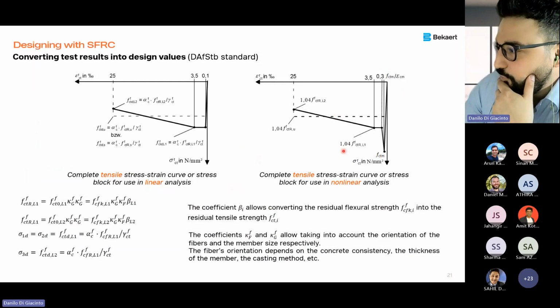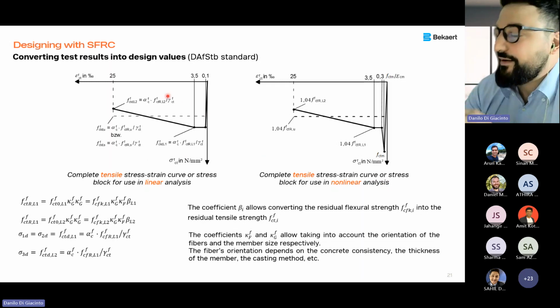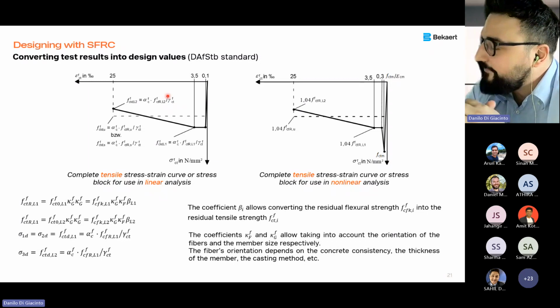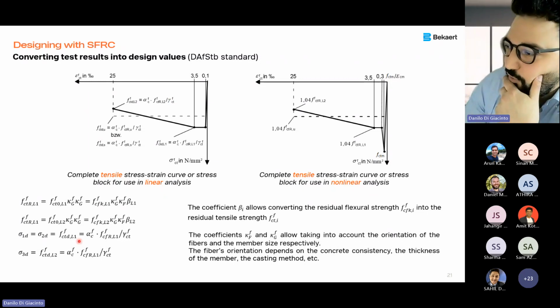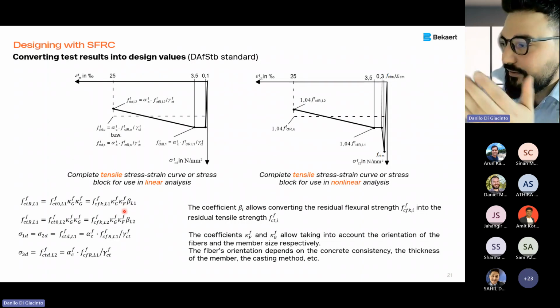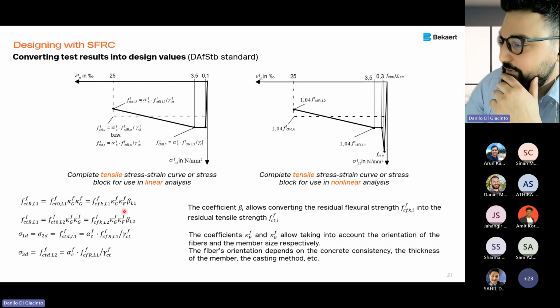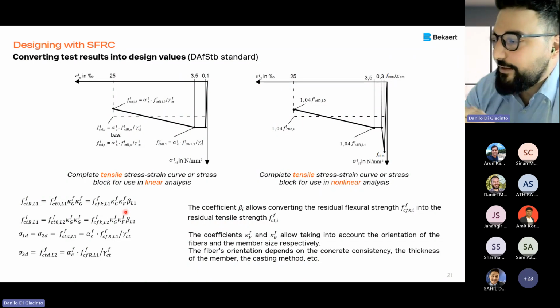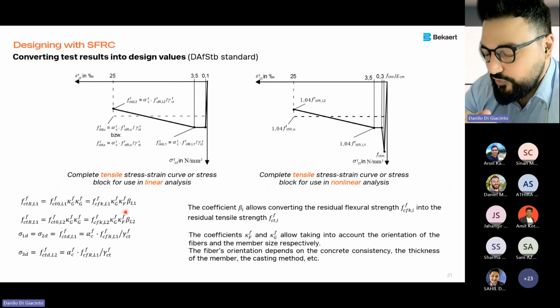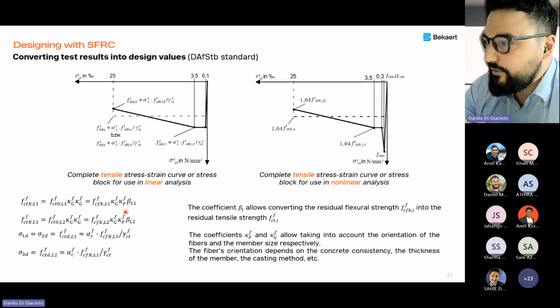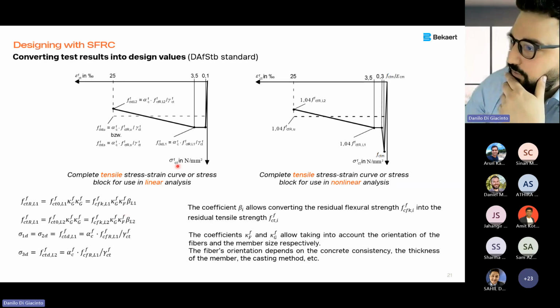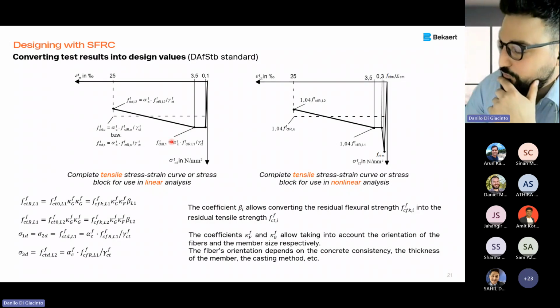This is a nice slide with two tensile loads. This one is used typically for linear analysis. This one is used typically for nonlinear analysis. Those tensile loads come from the German standard, which I told you is very comprehensive and covers every aspect of SFRC. You can see here the coefficients I was talking about previously, and those coefficients depend on the properties of your concrete and the element you are investigating. There are very simple formulations to handle and convert residual flexural strength values to tensile load, and at the end to the design values you will use for your design.